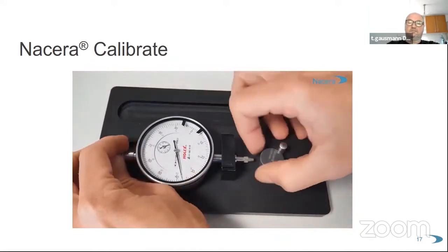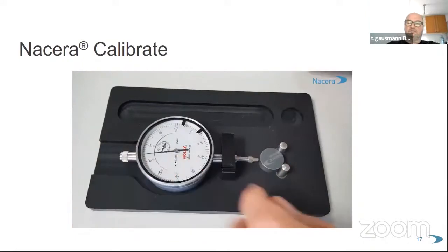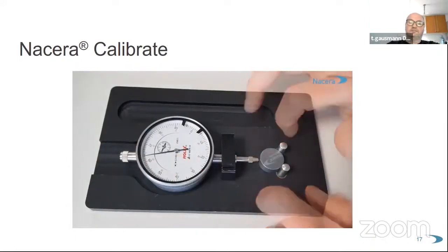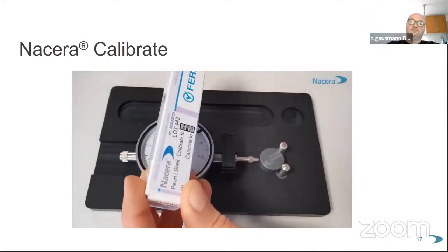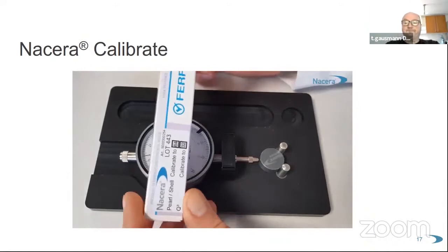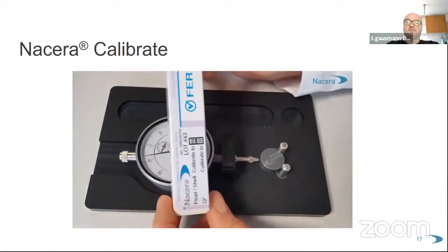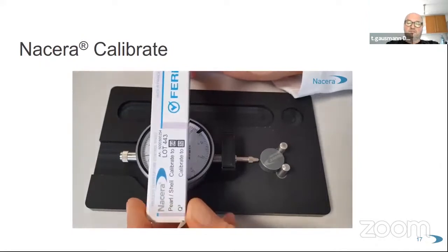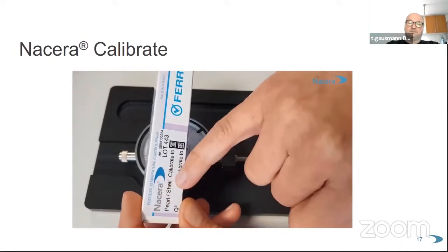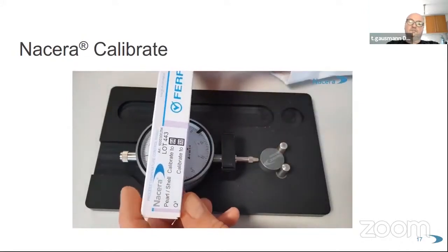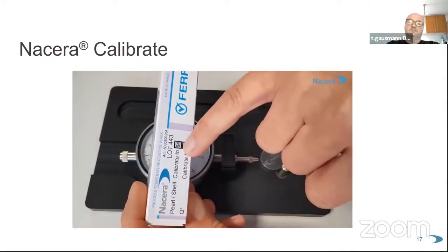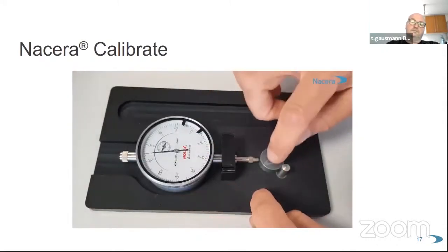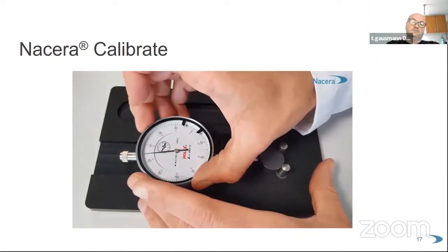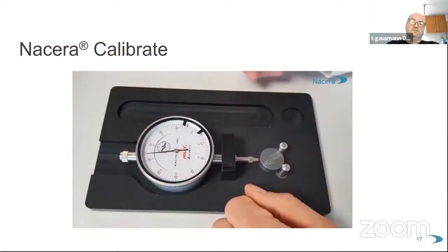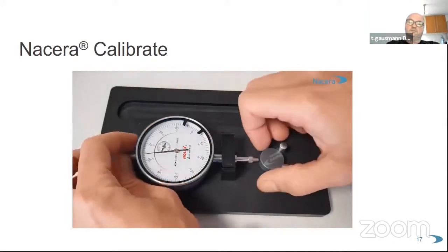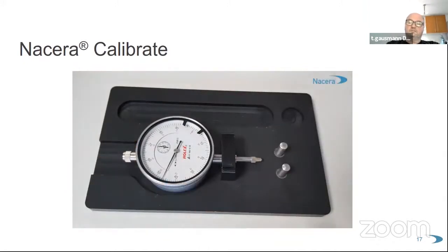Insert first the gray calibration body into the device. Tap slightly the base plate to align the calibration gauge. Set the gauge dial to the material-specific value given on the ceramic ring's packaging. There are different types of lots available. Here, for example, we sintered 3Y-TZP Pearl material at 1500 degrees Celsius. With Pearl, we have to calibrate to 64. With the gray body still positioned, turn the dial gauge until it indicates 64. Replace now the calibration body by the sintered ring and read the value.